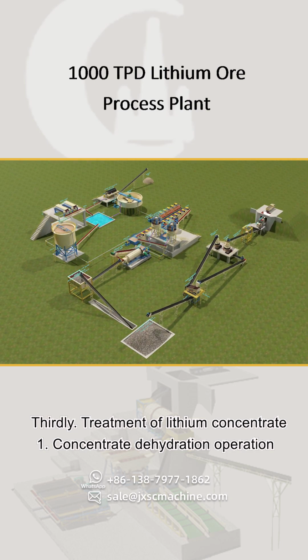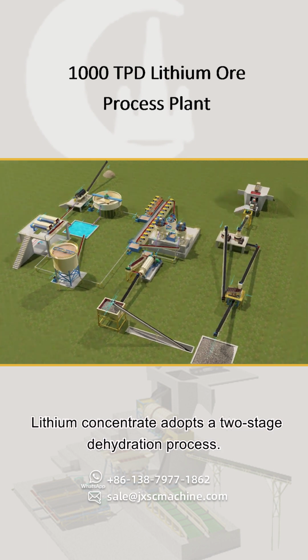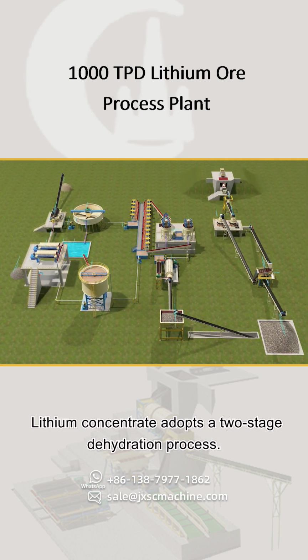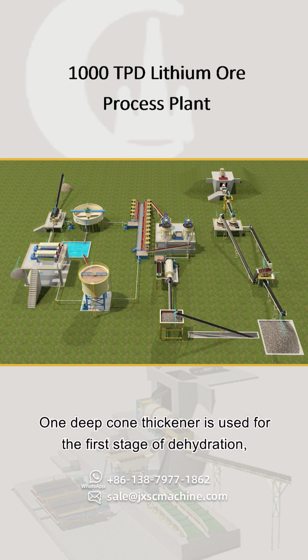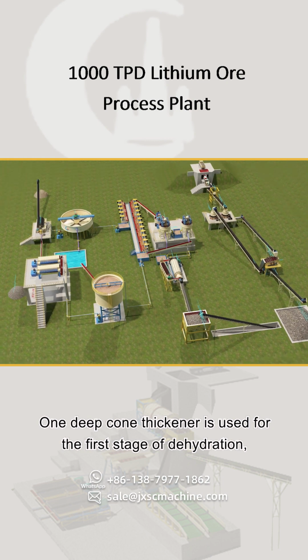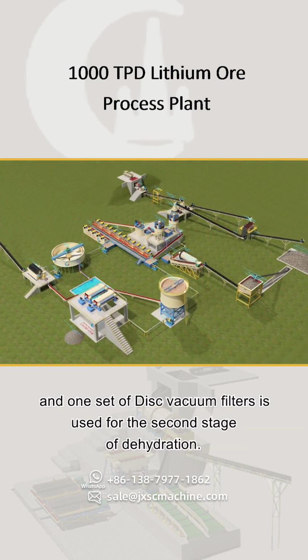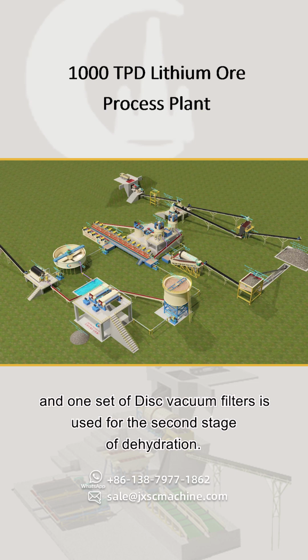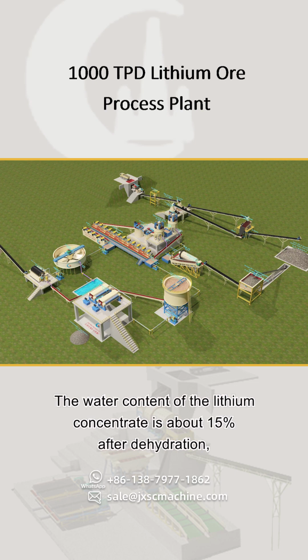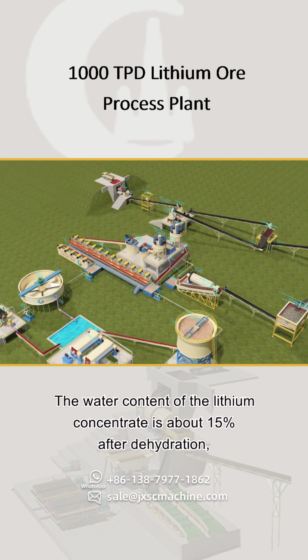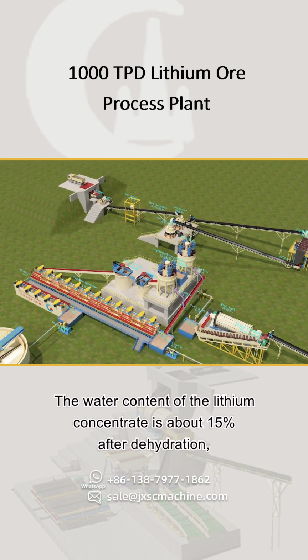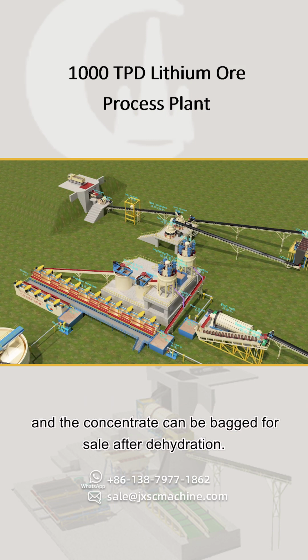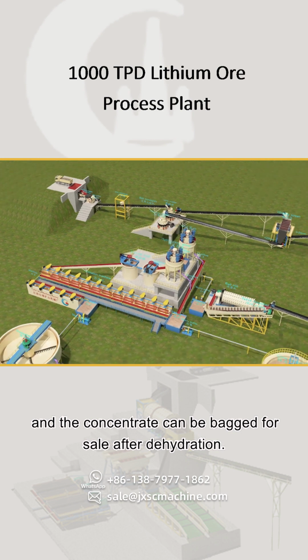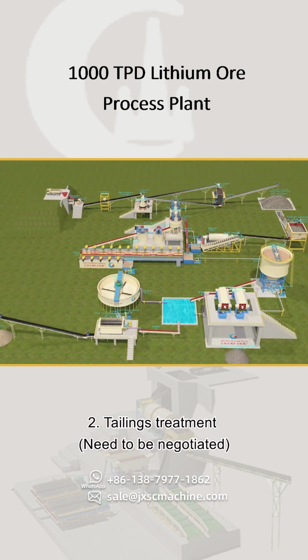1. Concentrate dehydration operation. Lithium concentrate adopts a 2-stage dehydration process. 1 deep cone thickener is used for the first stage of dehydration, and 1 set of disc vacuum filters is used for the second stage of dehydration. The water content of the lithium concentrate is about 15% after dehydration, and the concentrate can be bagged for sale after dehydration.